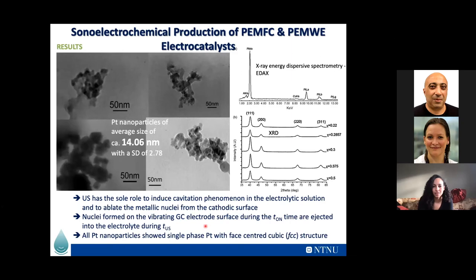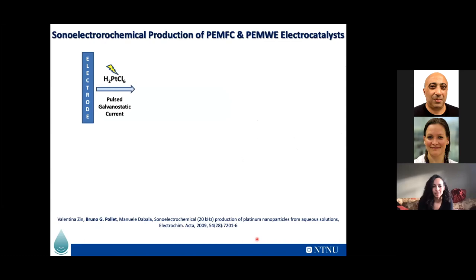We also found out that all the platinum nanoparticles formed at the surface were a single phase, which was actually an FCC structure, of course. I mean, it would have been so nice to find a different structure with the ultrasound, but that's another topic of research. So what do we have? You have your chloroplatinic acid, an experiment at the electrode. You're actually forming your nanoparticles on the surface, a blast of pulsed ultrasound, and then you've got your platinum nanoparticles.